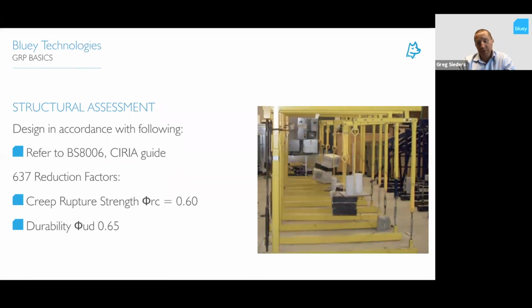On the creep rupture, we apply a 0.6 reduction factor. What that means is anything below 60% of load, the GRP bar won't rupture. And then for a durability factor, we put 0.65. That's a conservative number based on the standards, but when you add both of those together, we're using a maximum of 40% capacity of the GRP bar. So at that point, we'll never have any creep rupture because we're only at 40% capacity, and there's still a lot more redundancy in the design and in the leftover capacity of the bar.